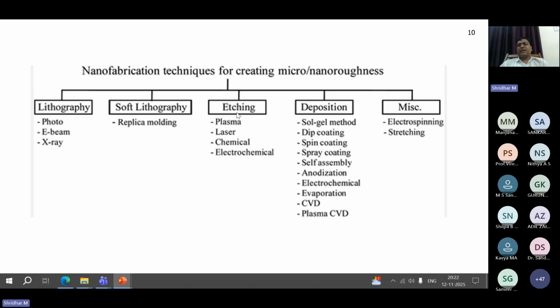Next, etching is the third method for nanofabrication. Etching can be done using plasma or laser etching, or chemically we can etch substrates, or electrochemically you can etch these substrates. Here, plasma means we supply a high amount of voltage, approximately 800 volts or 400 volts, and this is done in a controlled atmosphere like argon or neon or nitrogen. Then only can we etch the material without any defects.